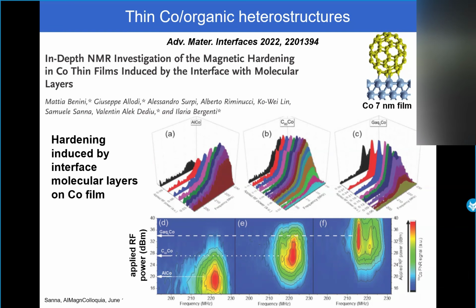This is the applied radio frequency power. So let's say the radio frequency field, somehow related to the radio frequency field. You can see that in this material, which is simply cobalt, in this material, which is cobalt covered by fullerene, in this material, which is cobalt covered by gallium-quinoline, you can see that for the two materials covered with the molecular layers, the power requested is higher to get the maximum, which means that there is a hardening of these magnetic cobalt films induced by the interface coupling with the molecule.